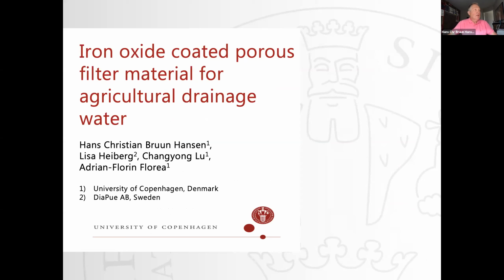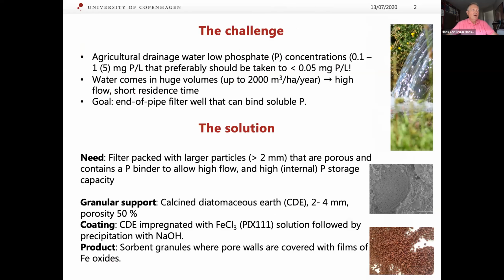So I will present, we have been in a project similar to the one Thilo is now running. It was called Supreme Tech, a project to look at phosphorus filters in the landscape. And essentially there are two types of filter materials to trap P: alkaline materials, calcium-based usually, that are based on precipitation, and then there are metal oxides, iron or aluminium oxides. And we've been working with the last type of filter materials, and actually it was a spin-off from this filter. So as Thilo also said, there's a lot of phosphorus stored in soils. It slowly is released. The concentration in agricultural drainage water is usually low, but we want to make it even lower to prevent eutrophication. Another challenge is that the water comes in huge volumes.